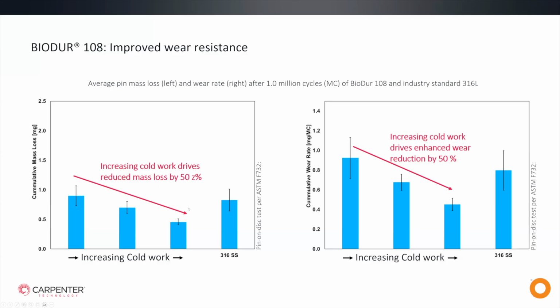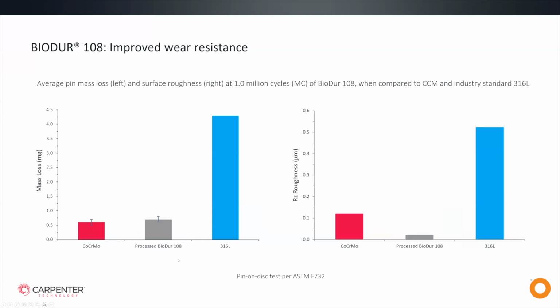So this is dramatically beyond that of what you would expect in a 316 stainless. And again, just to reiterate, this is strain hardening or cold work only. But we aren't here to talk about BioDur 108 as a potential replacement for 316L. That possibility is rather obvious. Instead, we're here to discuss the options for BioDur 108 as a potential replacement for cobalt-chrome molybdenum.